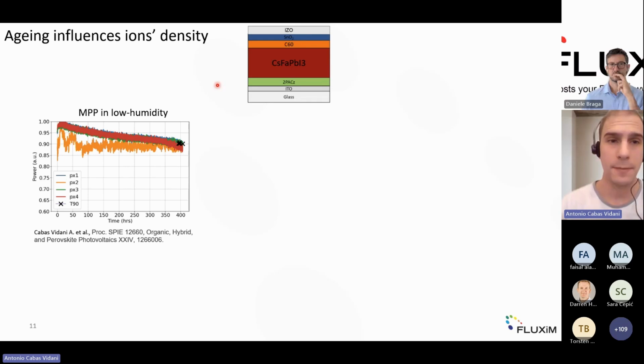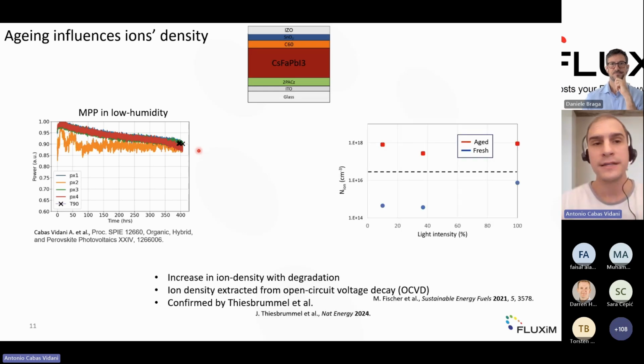We first of all performed MPP tracking of a very specific perovskite absorber. This is a cesium-based FAPI, and the device is intended for bifacial applications. We performed it in low humidity, and we could reach up to 400 hours T90 in this case, so up to 10% loss of the initial performance. And we combined that with rather advanced characterization. What we wanted to see was if there was any change in the density, mobility, anything related to mobile ions.